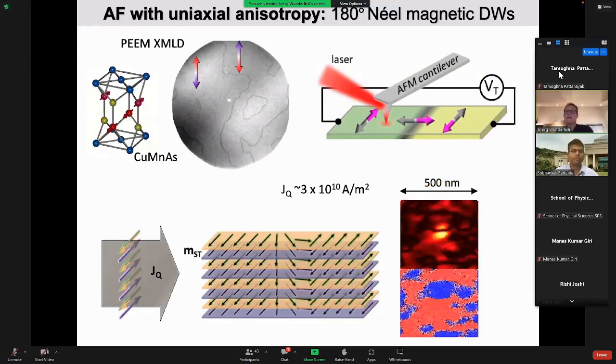If it were a 90-degree domain wall, you might move them, but in a totally different way. They would not reduce or enhance, they would just maybe shift parallel or something like this. But here it's really like a Zeeman field acting on ferromagnetic domains. They either enlarge these domains or reduce them. It's very similar.